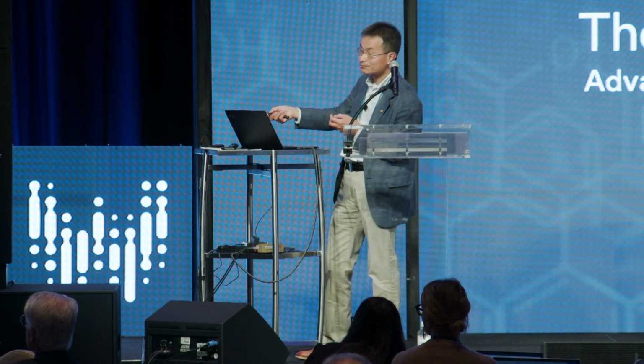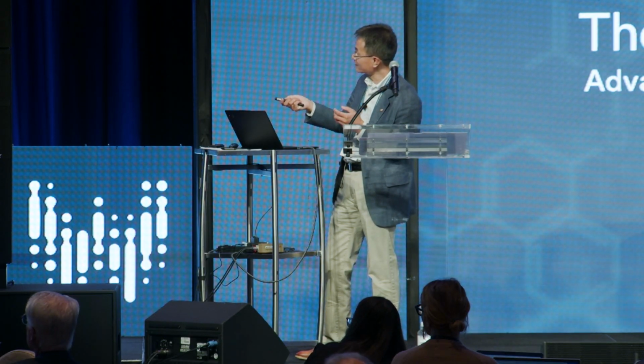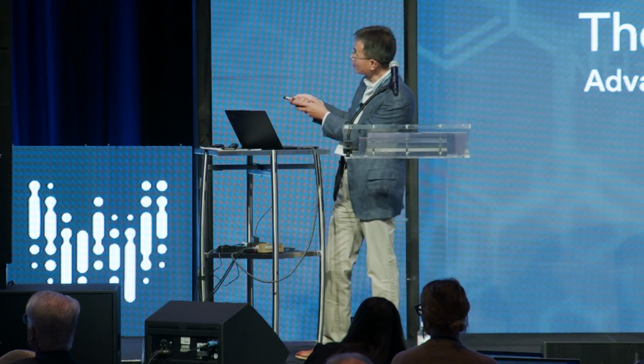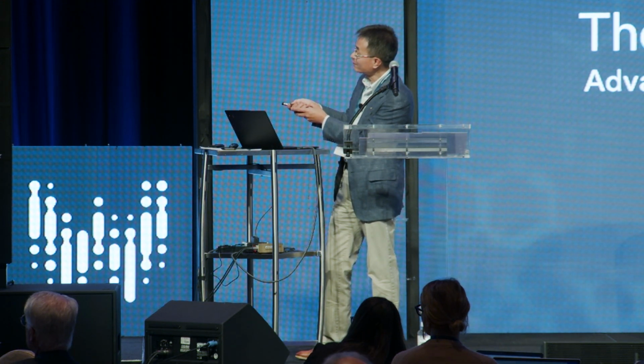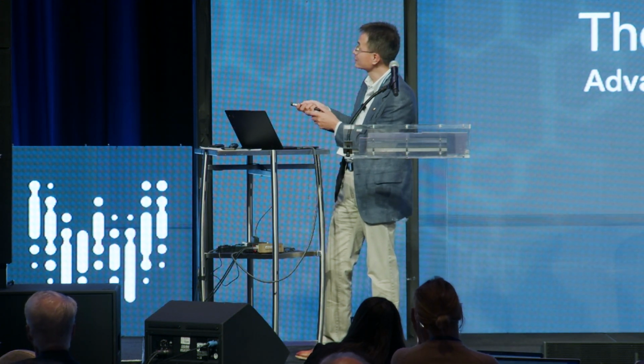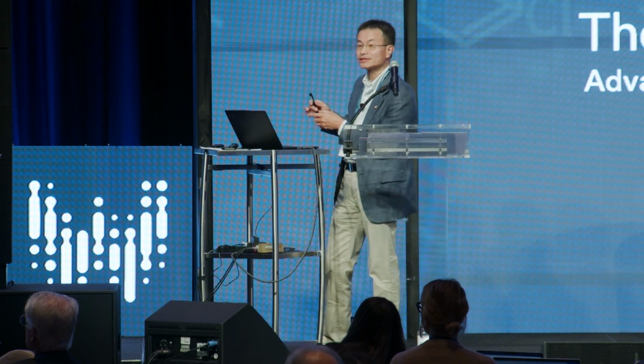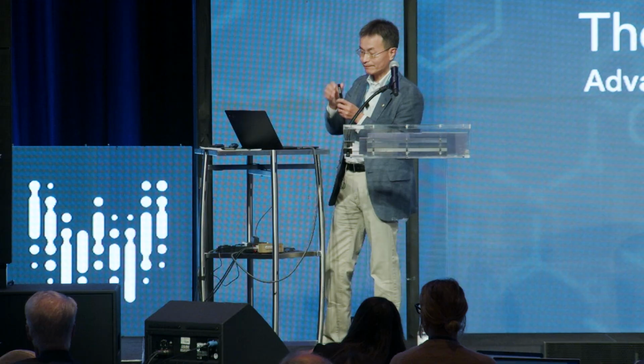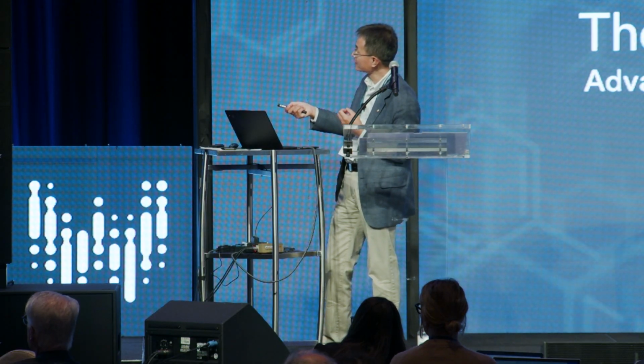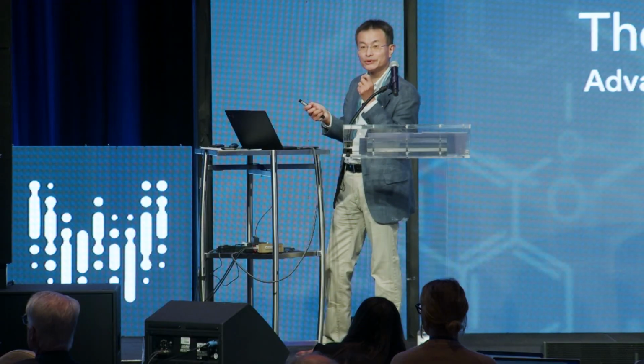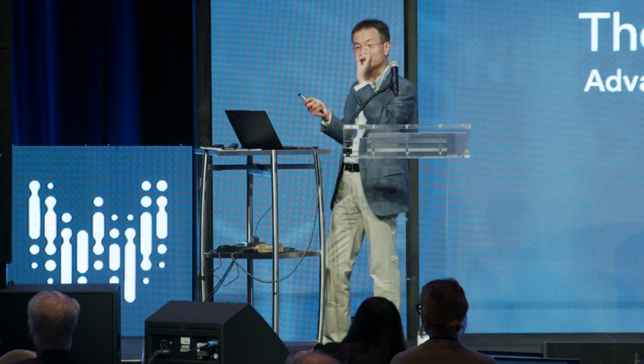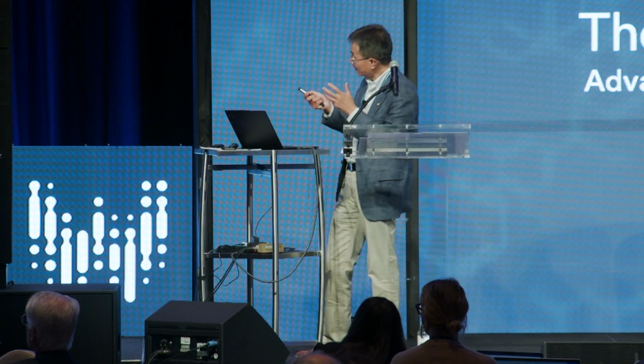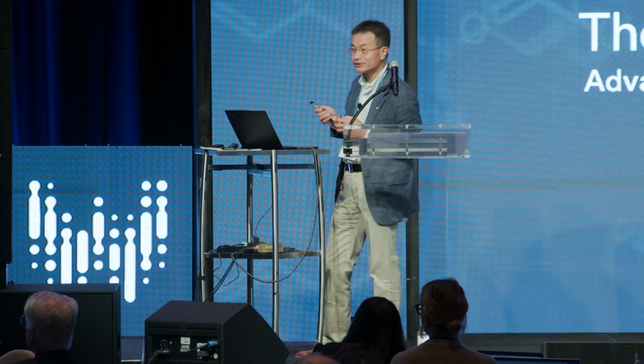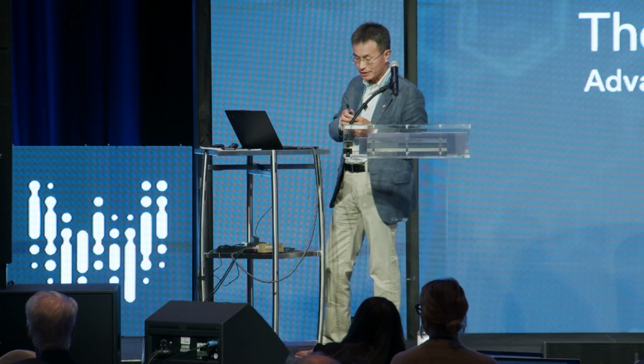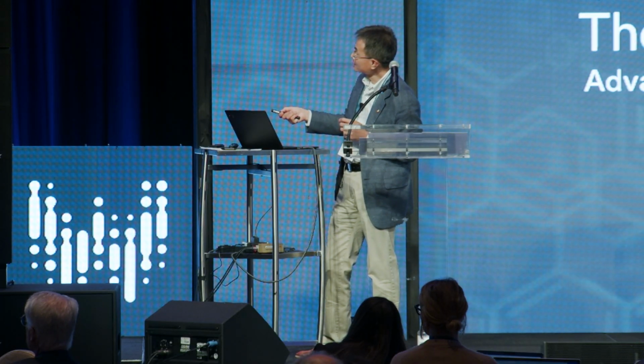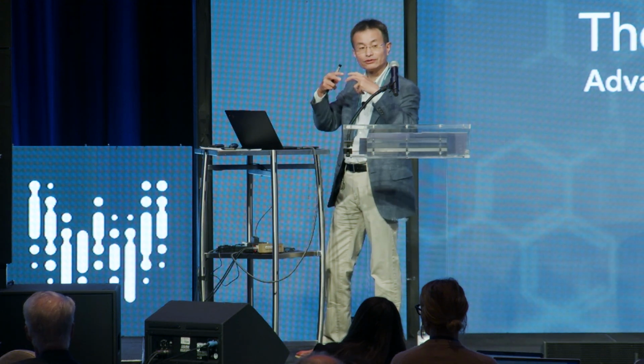Eventually, you see this thing pop. You will see many of these pop instantly. The popping of this dark contrast and light contrast is the biphasic region. It's telling you we're getting into this biphasic region. The dark spots are our gold-germanium liquid, and certainly gold is heavy, so it appears dark. The light spots here are pure germanium, so you are seeing a baby germanium nanocrystal starting to come out. Once you establish this liquid-solid interface, the rest is basically promoting one-dimensional crystal growth. More vapor goes in. It will first go into the liquid surface because the sticking coefficient is higher.